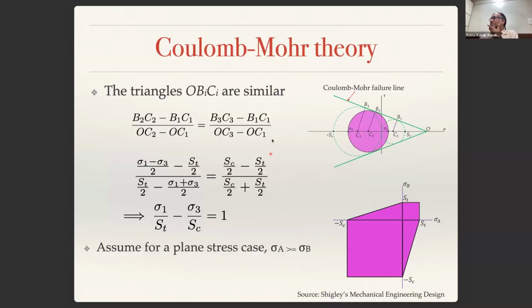So when you have similar triangles, you can write this equation: B2C2 minus B1C1 divided by OC2 minus OC1 must be equal to... How did we draw the third circle? The third circle is a state of stress which is not pure tension and pure shear, but corresponds to a stress state sigma 1 and sigma 3. And we have chosen that in such a way that it actually also fails. That is why it becomes tangent to the line. The moment it becomes tangent, it fails, no? That is a failure line. So this circle represents a state of stress that is actually failing under this combined loading. Is that clear?